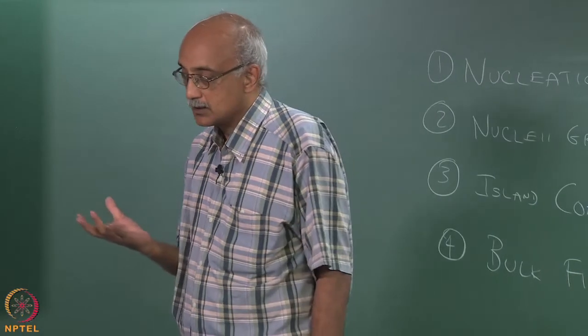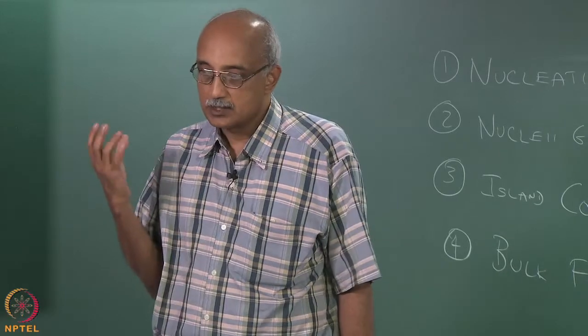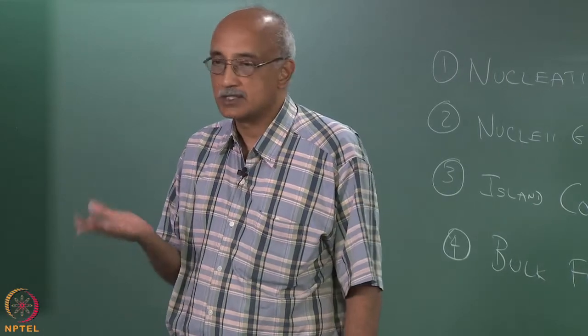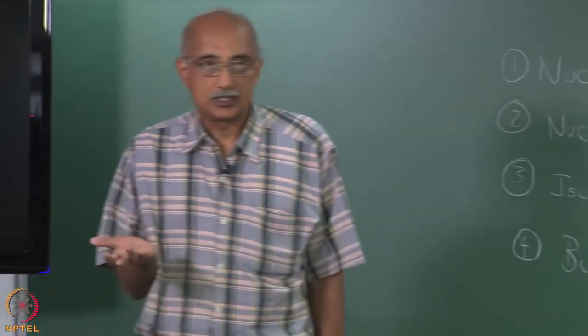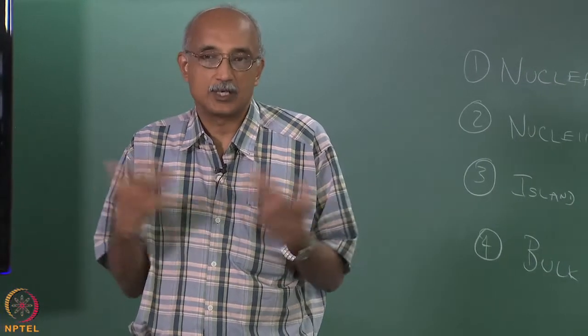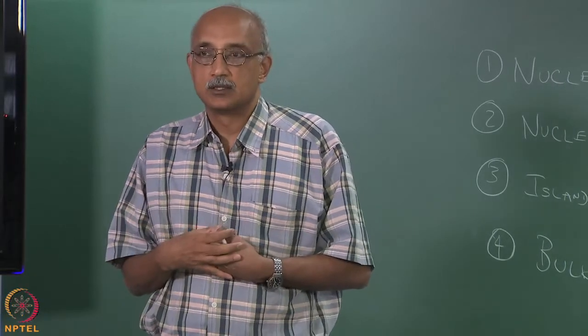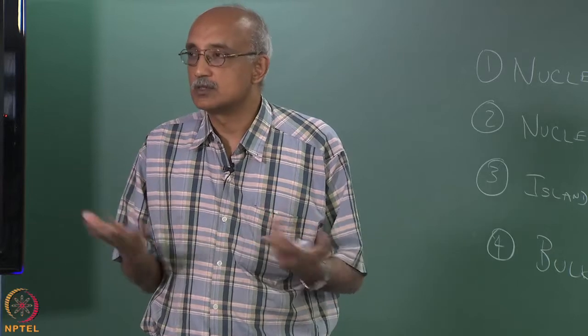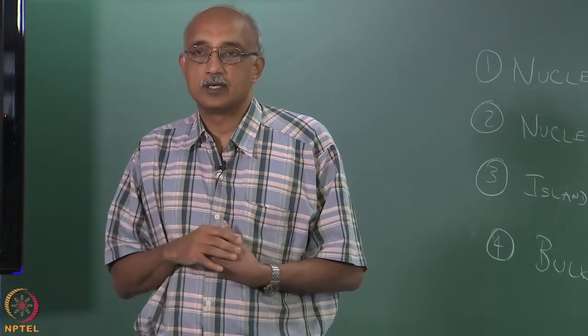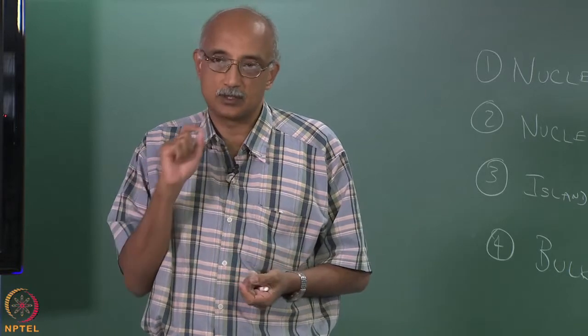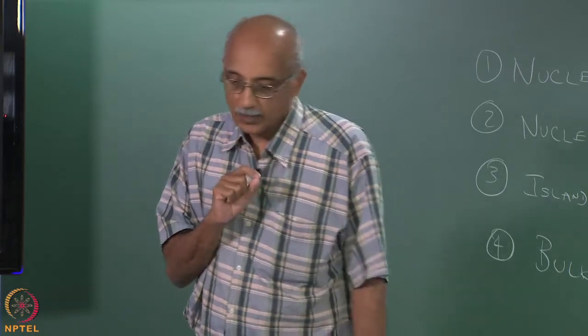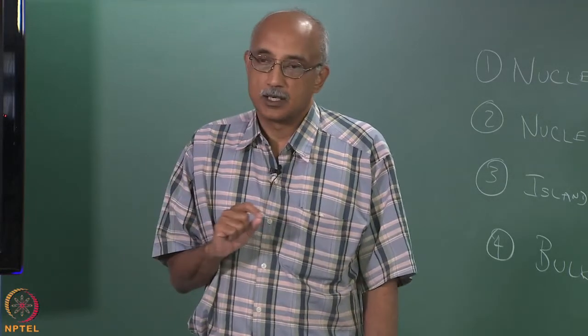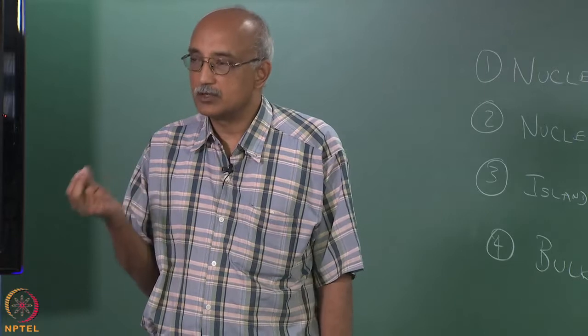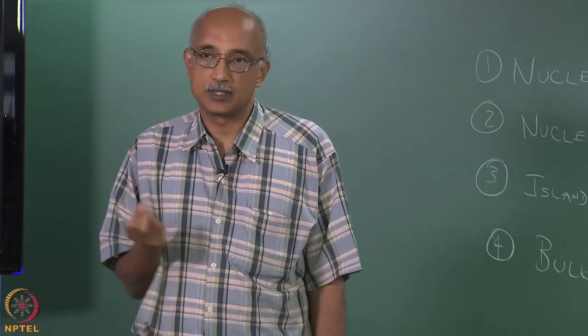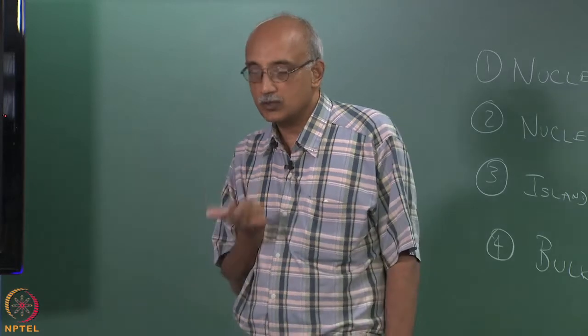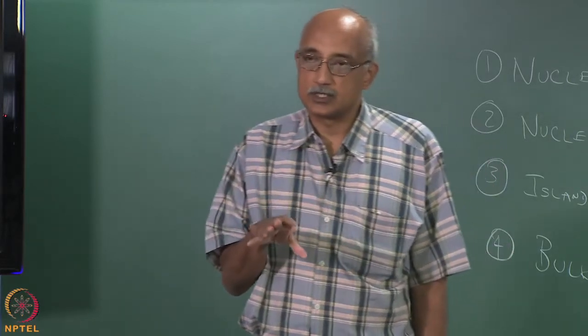Or in other cases, for example, if you have some impurity that enters your CVD reactor, for example, oxygen is frequently an impurity in CVD systems, because unless your CVD reactor is hermetically sealed, it's very difficult to prevent air from seeping in, which is mainly O2 and N2. N2 is relatively inert, so usually doesn't bother us, but oxygen, if it seeps in, can certainly affect the composition of your deposit. Another one is water. It's very, very difficult to keep moisture out of CVD chambers. So oxygen and H2O are frequently contaminants that will enter your CVD system.